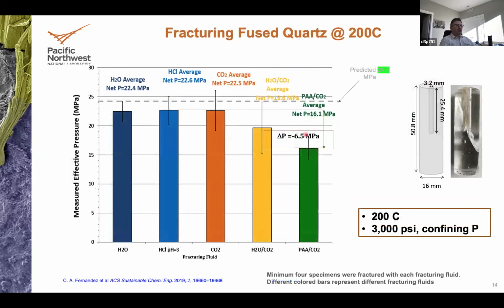So what we did is, well, rocks are obviously heterogeneous in nature, so we had to find something more homogeneous, and we used quartz, or actually fused silica. This is a non-porous material, and we prepared samples. We bought the samples from a third party, but with the same geometry and wellbore geometry as well. And we wanted a surrogate that is very homogeneous. We know by simulations at what pressure it will fracture, 24 megapascals. And we tested several fluids, including water, at least in triplicate. We fractured this, and it always fractures at a 45 to 50 degree angle.